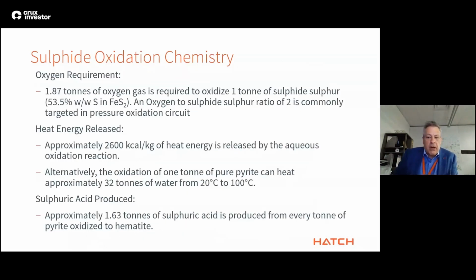The main reagent cost in the treatment of refractory sulfide ores is the oxygen gas needed to oxidize sulfide sulfur. Typical oxygen gas requirement for pressure oxidation is 2 tons of oxygen per ton of sulfide treated, just slightly above the stoichiometric value of 1.87. The heat release from the aqueous oxidation of 1 ton of pure pyrite is approximately 2,600 kilocalories per kilogram of sulfide. This is sufficient to heat 32 tons of water from 20 degrees Celsius to 100 degrees C, which is an important feature of achieving and maintaining autothermal operation.